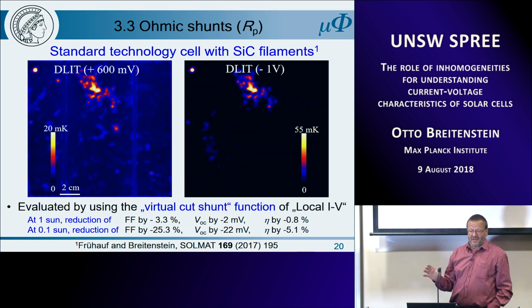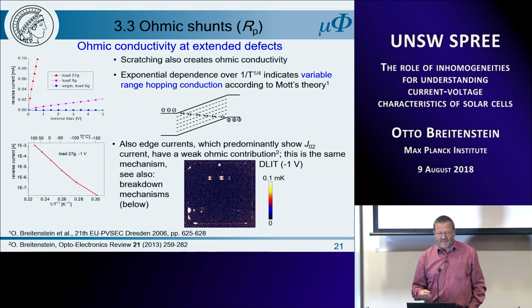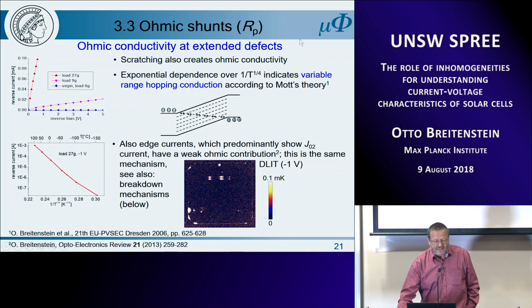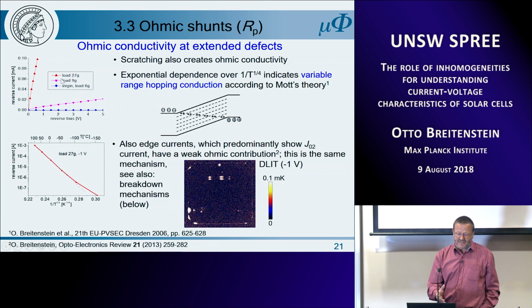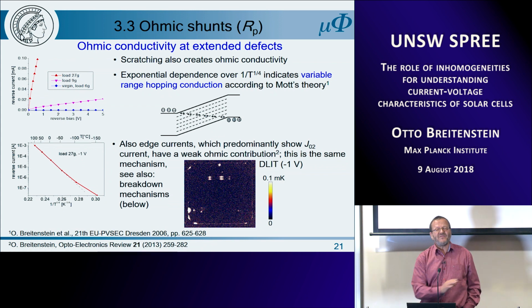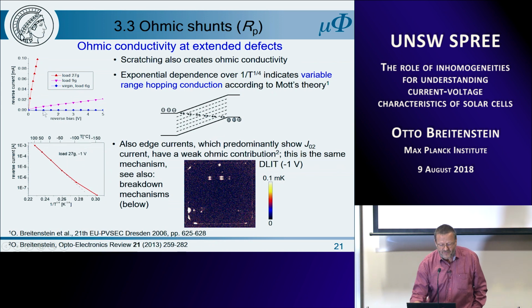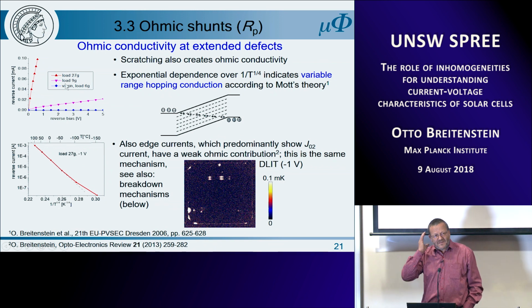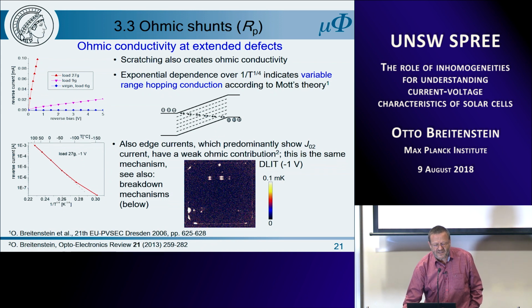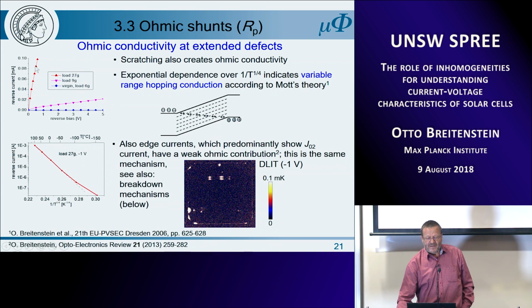But there are other ohmic conductivities, and the most interesting one is also ohmic conductivity at extended defects. This also was made by these scratching experiments. So the virgin solar cell did not have any measurable ohmic conductivity under low reverse bias. This is reverse bias. But depending on the load, the stronger the load is and the closer we come to the p-n junction, and if we cross the p-n junction with the diamond, then we get some ohmic conductivity, also under reverse bias.